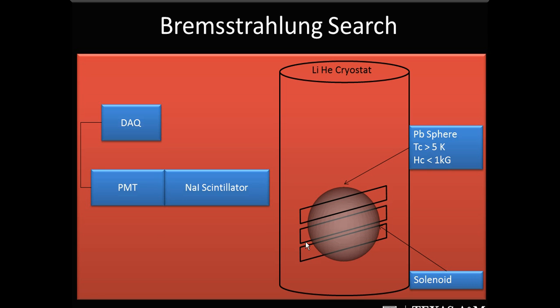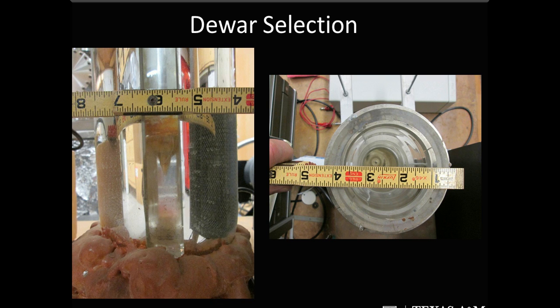We're going to take a lead sample, bring it into a superconducting state by cooling it with liquid helium, quench it by pulsing it with a 2 kilogauss magnetic field over the space of about 100 microseconds, and watch for the X-rays to come out using the sodium iodide scintillator and photomultiplier tube. So far we have gathered and characterized all the equipment we need for the experiment.